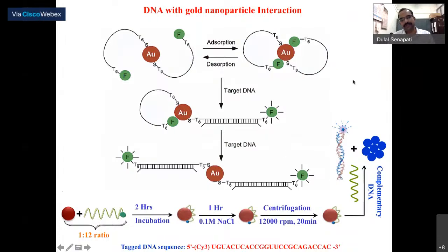How we can design them is simply to think about a DNA chain. One side has a thiol linkage and the other side is a fluorophore. Gold has a huge affinity towards thiol, so easily it can attach at one end, and the other end, the fluorophore, can loop back and fall onto the surface of the gold. Once it comes close to the gold surface, it immediately quenches. Now, if we put in a target DNA which is complementary to this DNA chain, they will hybridize. Once hybridized, it is a rigid rod, so it will come out from the surface and go away from it. As a result, the quenching will be reduced. So by recording this, we can find out how long the complementary strand is.